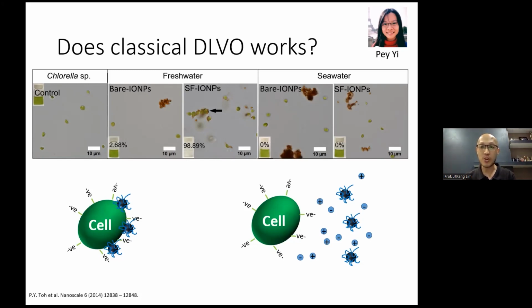And this ionic species actually provides something called Debye screening. That means if you have negative particles and positive particles, like a negative cell and positive particles, right? If you have a lot of free ionic species around, you will screen the interactions between them. So in fact, you really suppress the interaction, making it much weaker. However, this is not what we have observed.